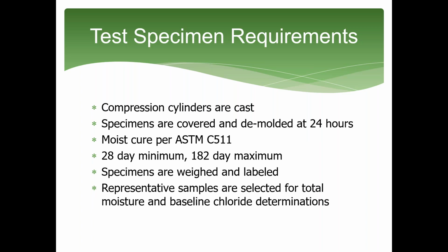We cast 3 compression cylinders with each batch. Specimens are covered and demolded after 24 hours of wet cure. The moist cure is in accordance with ASTM C511. The curing range is from 28-day minimum to 182-day maximum. When the specimens are ready for test, they are weighed and labeled, and then representative samples are selected for total moisture and baseline chloride determinations.